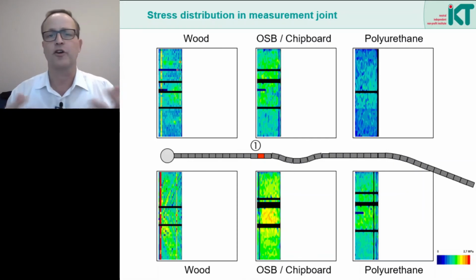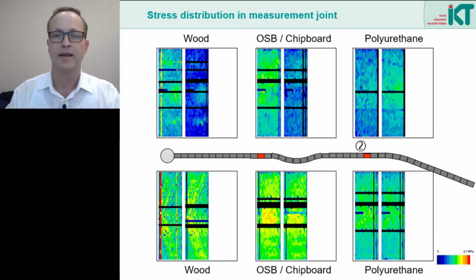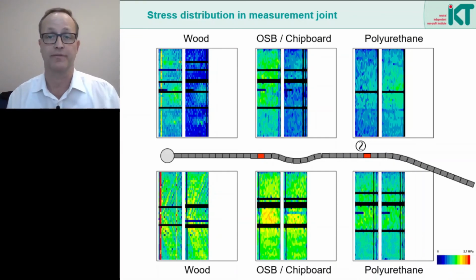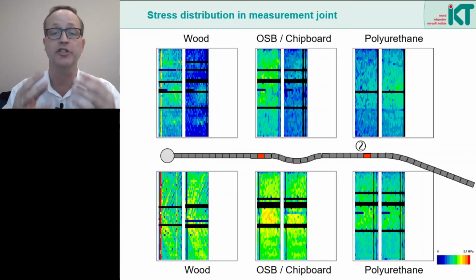This result, of course, is not surprising because the pipes were pressed steadily straight ahead to the virtual location at point 1. So differences in stresses can only result from geometrical imperfections, in particular from the unevenness of the concrete surface in the pipe joint. Here we see the second rectangles and the stress distribution after passing the steering curve. So we are now at the location of point 2.